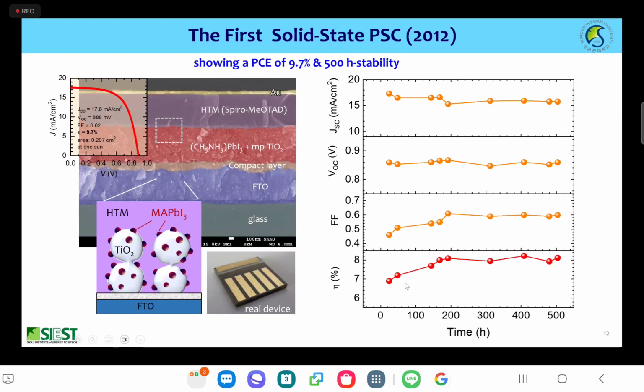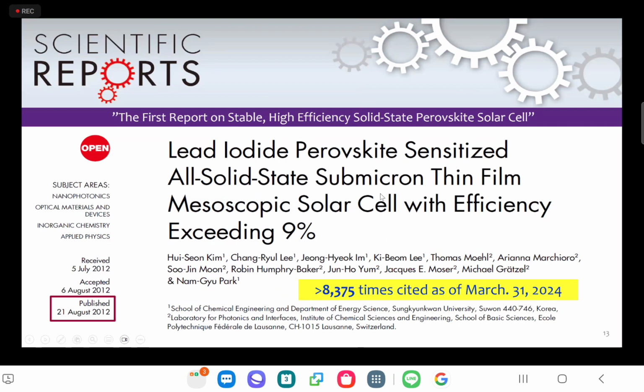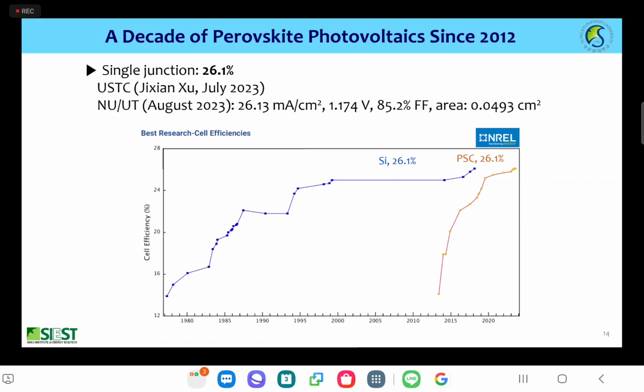We also showed a pretty stable configuration of these devices up to 500 hours. This is the encapsulated device stability. Finally, we reported this solid-state perovskite solar cell in Scientific Reports. Now the paper is cited a lot, and this is actually the first report on a stable, high-efficiency solid-state perovskite solar cell. Based upon this discovery, the single junction perovskite solar cell has now achieved a certified efficiency of 26.1%. Now 26.5% was certified.